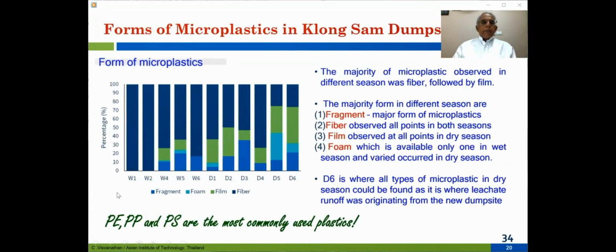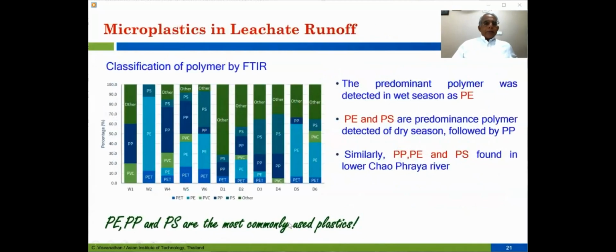So you can look at it very interestingly. We took samples in the wet season, and here we took the samples in the dry season. And it is very interesting. The fragments, for example single-use plastics, disintegrate with time, and the fragments become microplastics. In terms of microplastic, polyethylene, polypropylene, and polystyrene are the most commonly used here in this case.